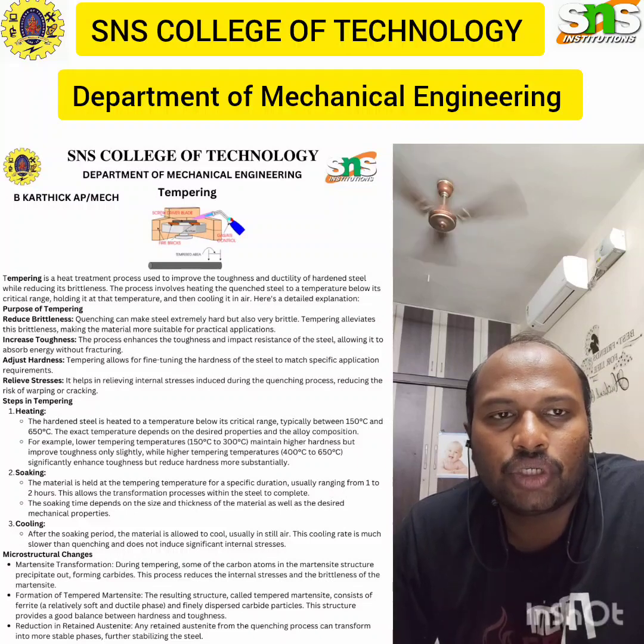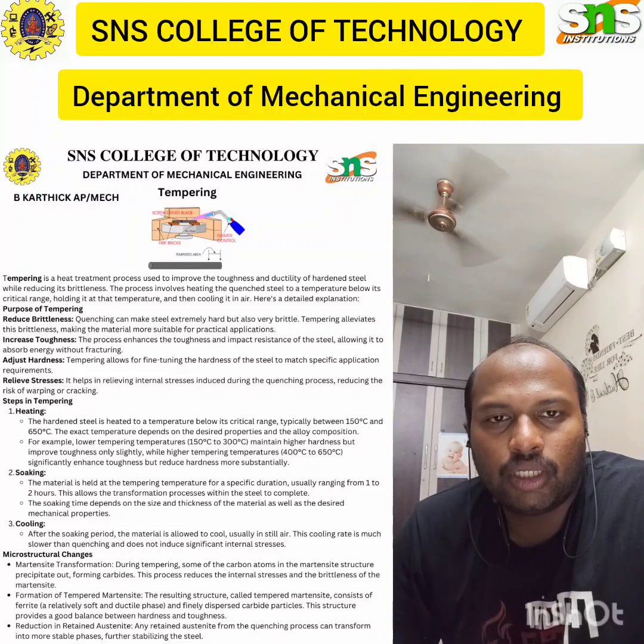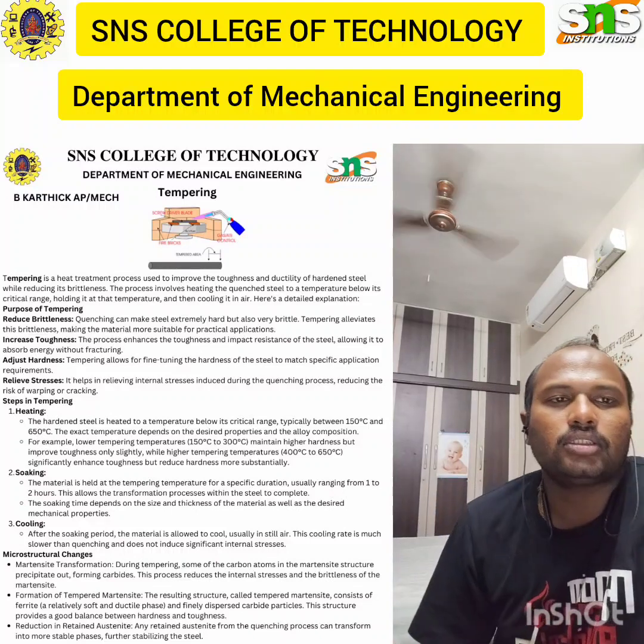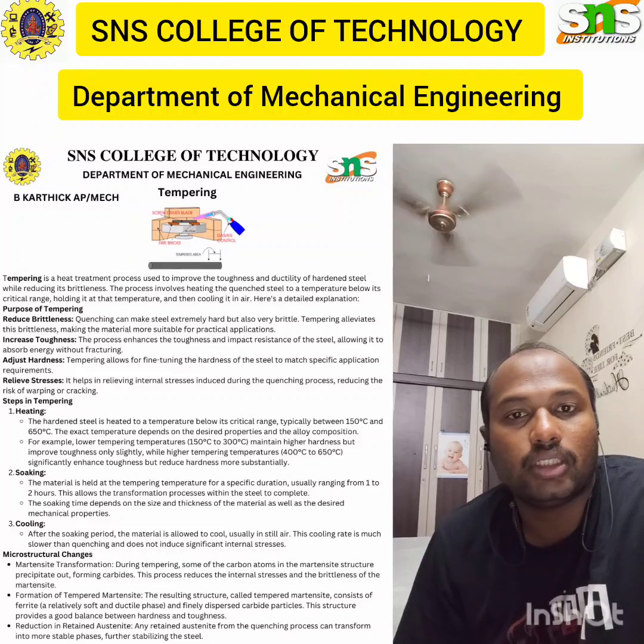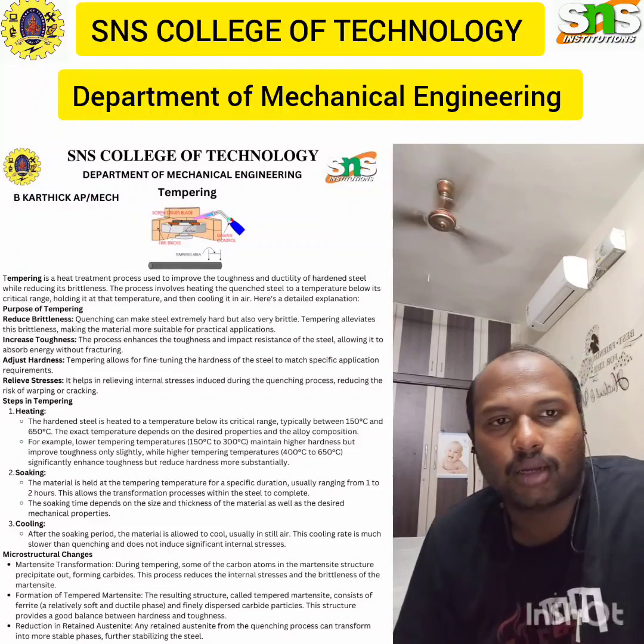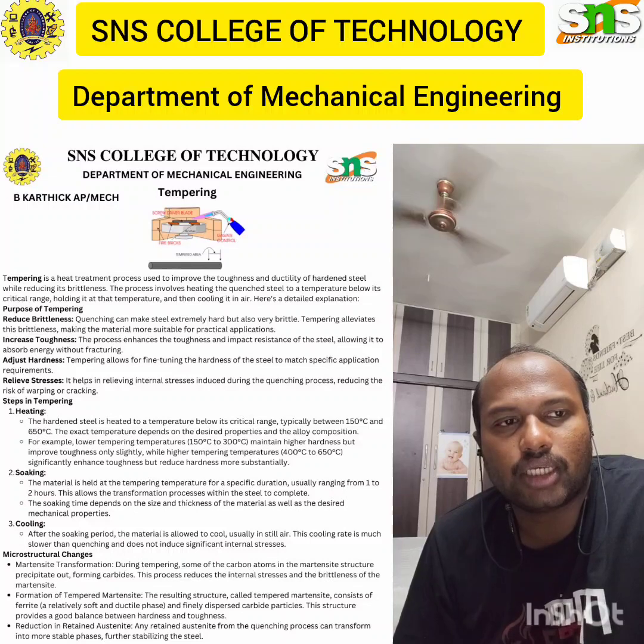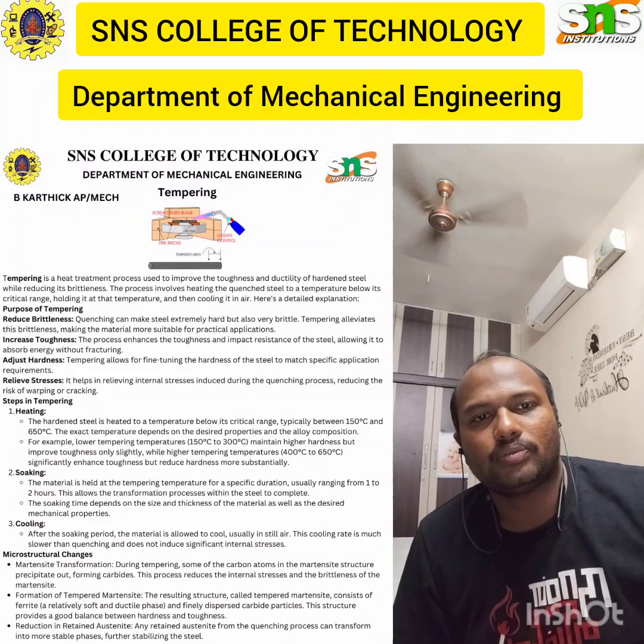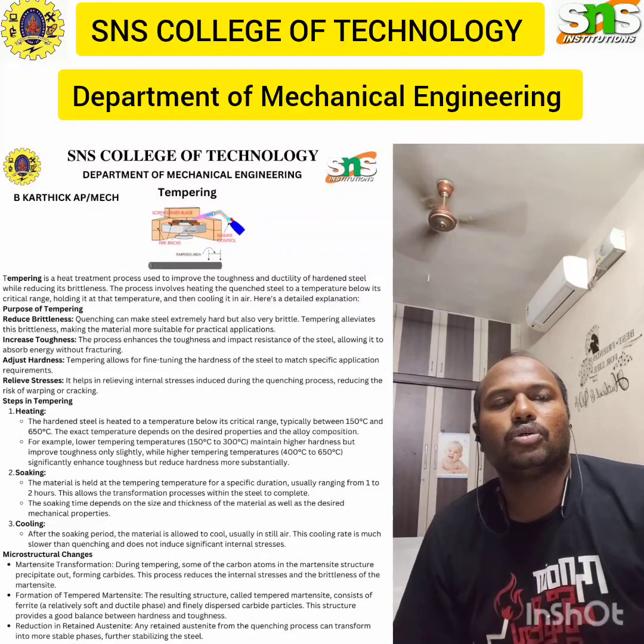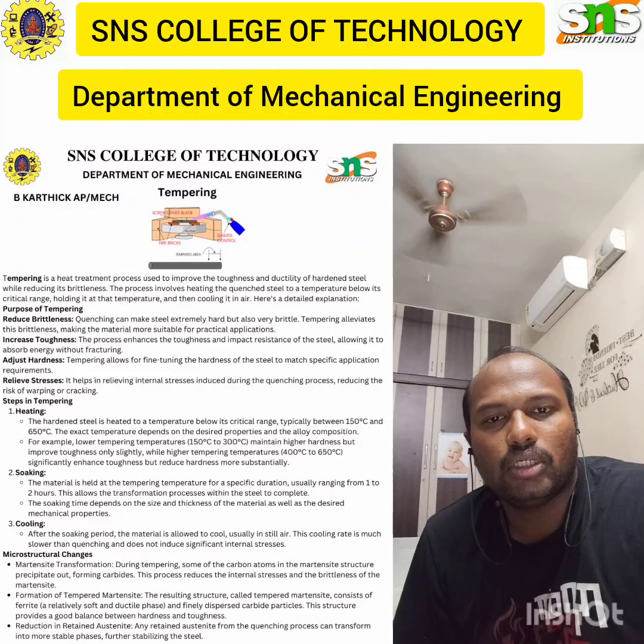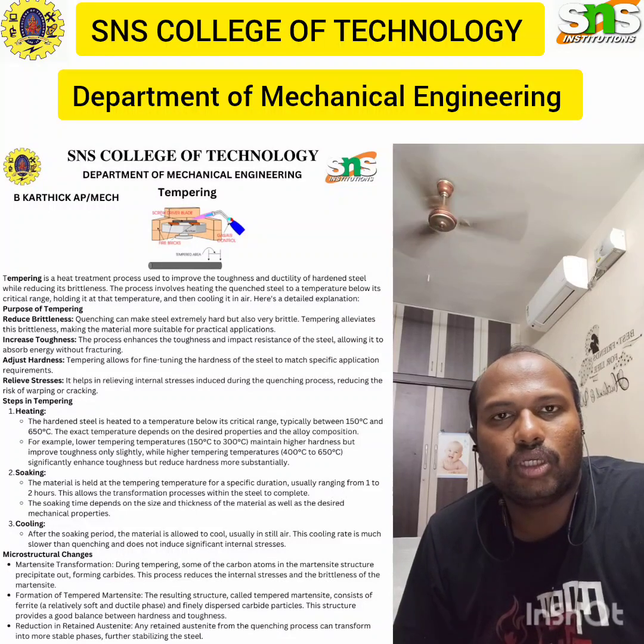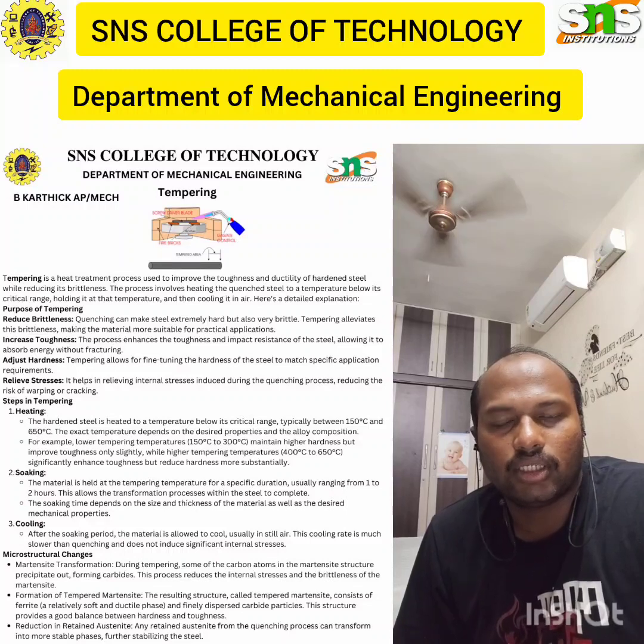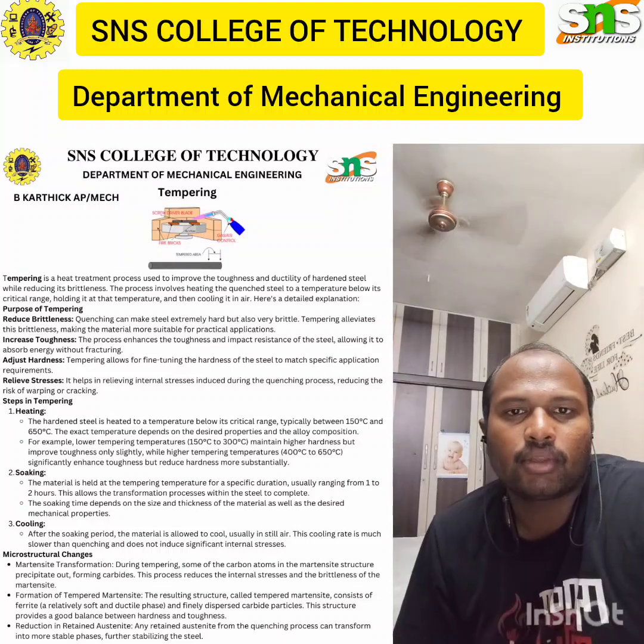In soaking, the material is held at the tempering temperature for a specific duration, usually ranging from 1 to 2 hours. This allows the transformation process within the steel to complete. The soaking time depends on the size and thickness of the material as well as the desired mechanical properties. Cooling: after the soaking period, the material is allowed to cool, usually in still air. This cooling is much slower than quenching and does not induce significant internal stress.